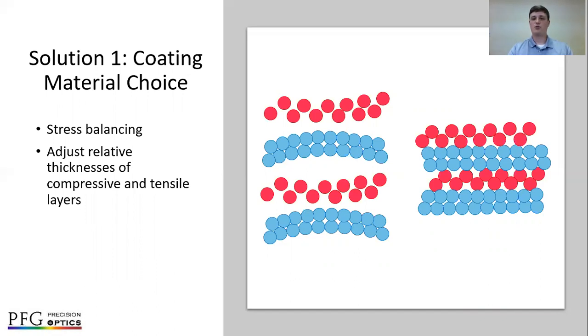You're, of course, limited by your ability to meet the optical requirements of the coating. Also, any environmental durability testing you have to survive, or perhaps even laser damage threshold. But generally, it's possible to find the right combination of materials that, when put in the proper relative thicknesses, will produce a stress-free coating. What's required to do this is extensive characterization of your coating materials and a good understanding of their individual stresses so that you can calculate the relative thicknesses necessary.